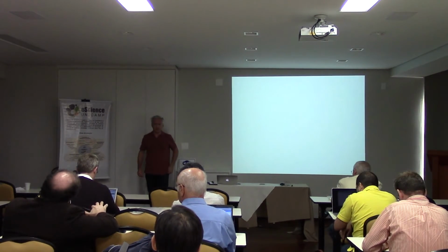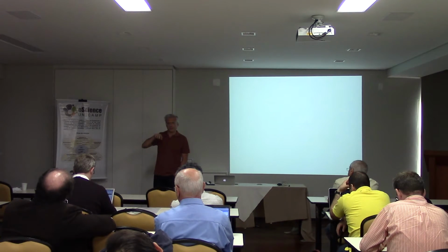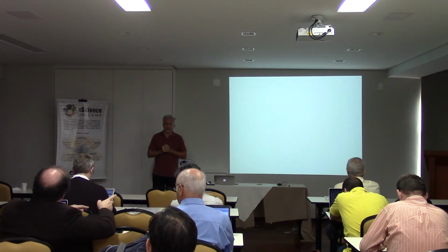For the nanoparticle experiments, at what voltage, low voltage, high voltage? I don't remember exactly all the voltages, but they also performed studies looking at the dependence on the voltage. So for a very broad range of voltages, the result is independent of the voltage. But do you know if at high voltage the electron beam has enough kinetic energy to sputter the sample or not? No. It's below the threshold.